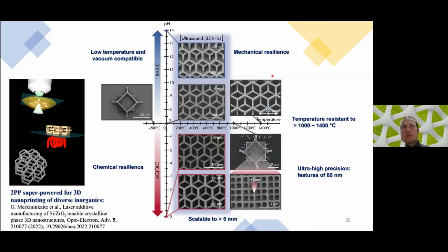Without going into details about other performed experiments, I would like to summarize the impact of resilience. It can be thrown into liquid nitrogen, at least down to minus 200 degrees Celsius or even lower temperatures, and straightforwardly extracted and left to dry at room temperature, coming back in seconds, because the structure is very small, instantly to room temperature, or being heated to 1000 degrees or above. Even if repeated, and as was shown, it is resilient to both basic and acidic harsh chemical environments, and to mechanical impact by ultrasound, and it also shows scalability from high precision features of 60 nanometers to overall dimensions scalable up to millimeters.